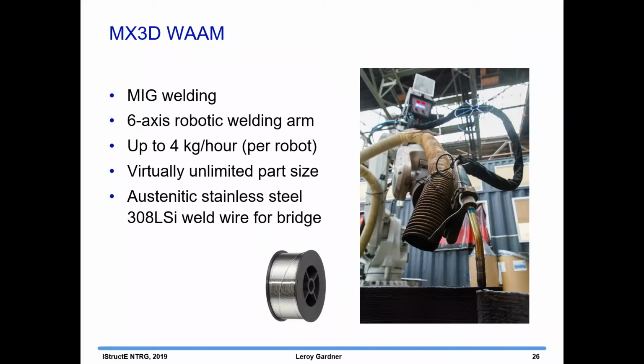The technology used to print the bridge is MIG welding in conjunction with a robotic arm. The robots can print 4 kilograms of material per hour, and the 3D printed part of the bridge was just over 4 tons. So it's about 1,000 printing hours, which is about 5 weeks full time. The actual printing process was spread over a longer period because there was various points of testing throughout the build process. The bridge is printed from austenitic stainless steel wire.